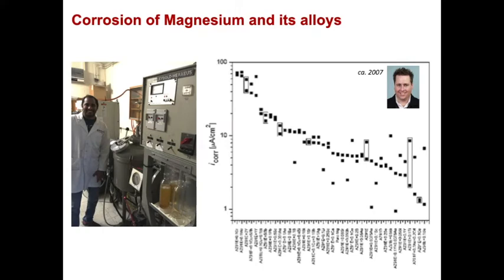All right, so I first started working on magnesium about 15 years ago now, or a little bit less, and my first PhD student that's listed there, Aaron Sudholz, carried out a project on alloying magnesium alloys with a range of diverse additions in order to see if we could reduce corrosion rates by functional alloying. In particular, we wanted to improve the corrosion resistance of the widely used magnesium alloy AZ91. The induction furnace, pictured on the left here with Shrevan, that did a project much later, is the furnace that was used to create over a thousand alloys in the past nearly 15 years. But in the case of Aaron's work, we found that essentially anything we added to AZ91D either had a negligible effect or, most often, deteriorated corrosion performance, and rather spectacularly, I may add.